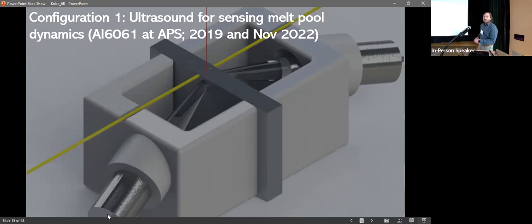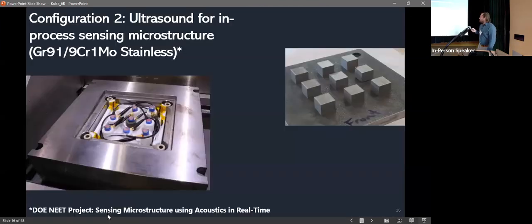We have the red laser actually creating the melt pool. And then we have these ultrasonic immersion transducers that focus the ultrasonic energy right where the melt pool is, that senses the melt pool dynamics. So that's configuration one. The other is ultrasound within the process.